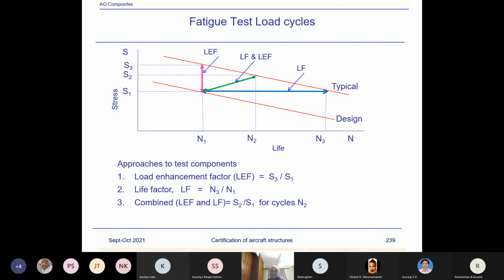The third method is to apply both, partly the life factor and partly the load enhancement factor. So now this is the common practice by the aircraft industry to evaluate the components, testing the components for the composite structures. So what is this? LF and LEF combined, S2 upon S1 for cycles N2. So generally, structures are tested around 2 lifetimes. N2 is around 2 lifetimes, 2 of N1.